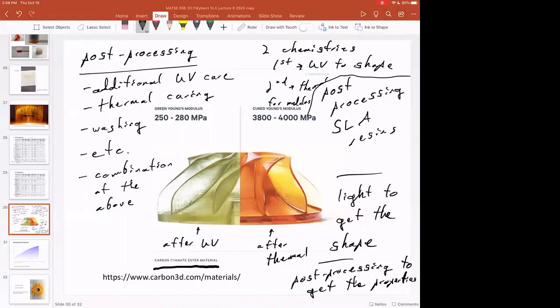But cyanate ester chemistry is not accessible by photopolymerization. And so in the mix of oligomers that Carbon uses for this material, they have acrylated cyanate ester molecules. And so they use the acrylates to shape the part using conventional SLA. Then they take that shaped part, put it in an oven, and then they activate the cyanate ester. And there you're able to do different sorts of chemistries at different times using different stimuli, which is really cool. If the polymer chemists in the class think about orthogonal chemistry or think about sequential chemistry that you can turn on at different times, they're doing exactly the same thing with these cyanate esters.